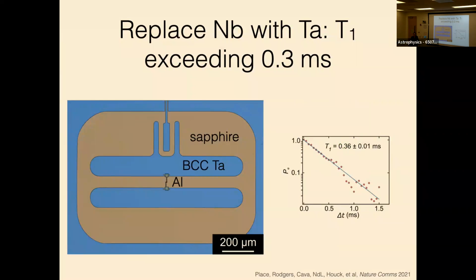So the punchline is that by replacing niobium with tantalum and being careful about our fab and contamination, we were able to break through this 10-year-long stagnation in superconducting qubit coherence and get devices that are robustly at a T1 exceeding 300 microseconds. So it was around a factor of 3 improvement over the state of the art. And let me emphasize here that the state of the art was at industrial fabs where you have a lot of control over the processing. Academic labs were not making 100 microsecond qubits by and large. They were making 10 to 20 microsecond qubits. So in some ways, this is an order of magnitude improvement over what you could normally do in your little academic clean room. And this is very robust. We have not made a qubit with under 200 microseconds with this material system.